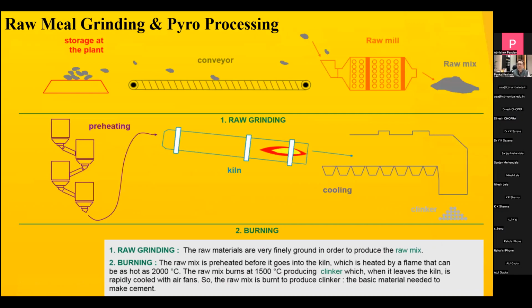The crushed material is then put through the raw mill, where it is ground into very fine powder. This powder is then blended, and then it is fed to the preheater. And from the preheater, it passes through to the kiln. In the preheater itself, it is calcined to about 98%. In the kiln, where the temperature is around 1400 to 1500 degrees, it is basically in the molten stage, and it forms the nodules, which are called clinker.